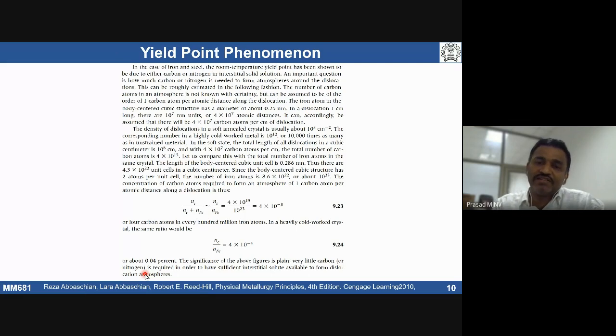The second method: in steels, the major culprit is the presence of these interstitial elements, which cause locking and unlocking that can lead to this kind of yield point phenomenon. If you can arrest those carbon atoms so that they will not directly interact with the dislocations, that means you need to arrest whatever free mobile carbon atoms are there in the low carbon steel. If you can arrest those free carbon atoms, that can also solve the problem.